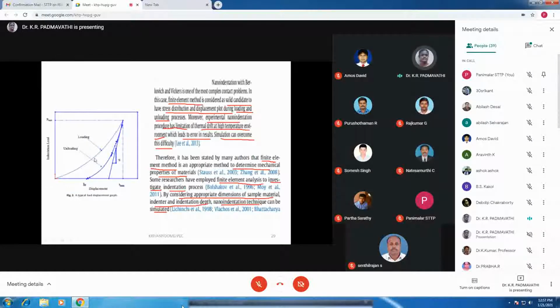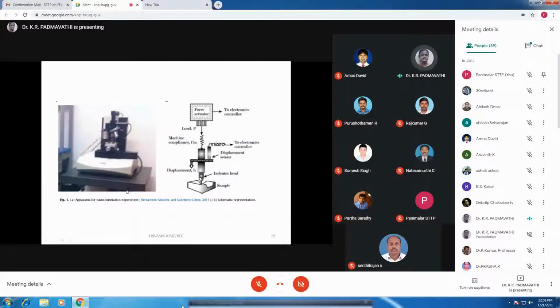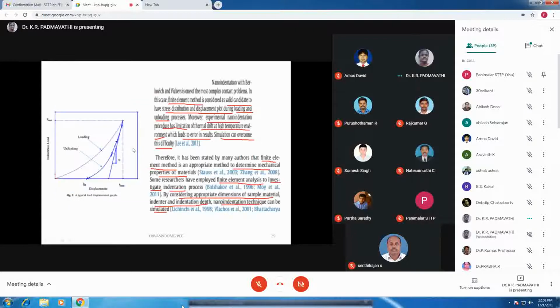Out of this experiment they got this loading and unloading curve, as I've already told you, from which the rate of indentation load to displacement we can get by drawing a slope on the unloading curve. Here the finite element method is considered a valid candidate to get the stress distribution and displacement plot during the loading and unloading process. The experimental nano indentation procedure has the limitation of thermal drift. Since it is a nano size instrument, they have to do the testing in a precise room environment at a critical temperature level. Due to thermal drift at high temperature environments, errors arise in the results if they do nano indentation experimentally. So simulation with the help of FEM or FEA can overcome this difficulty of thermal drifting.